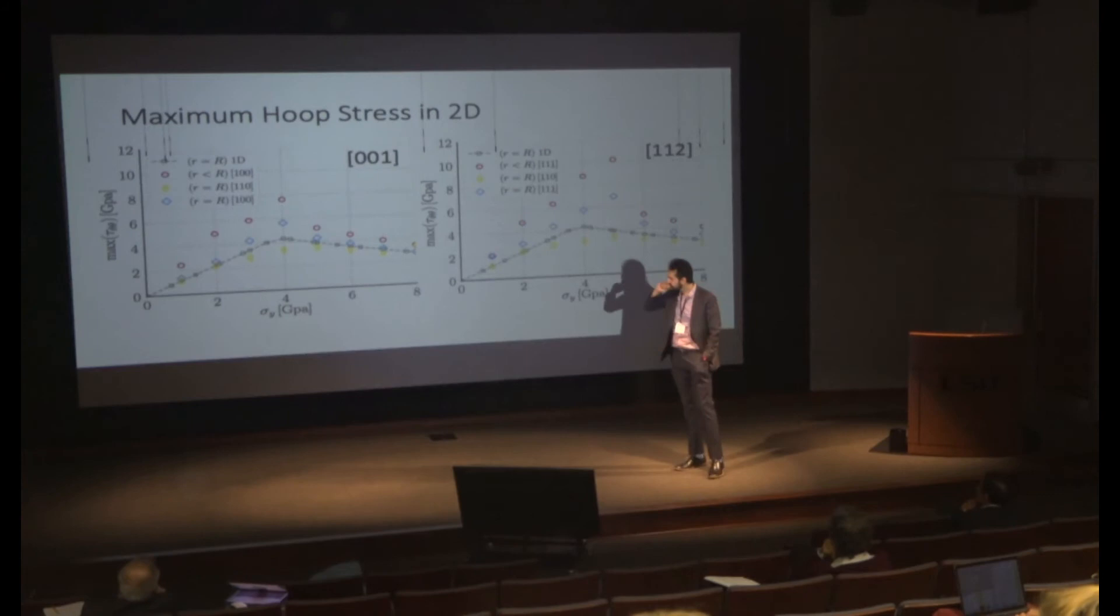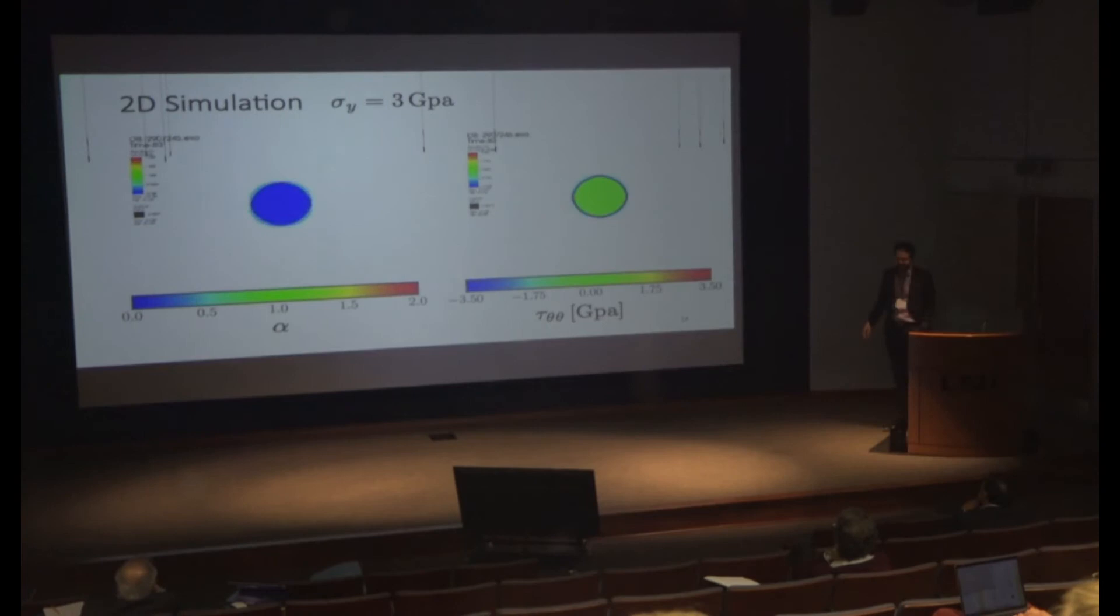Being a fracture person, what does that mean? That means if plasticity leaves enough room for you to get high enough stresses, you're going to crack. You're cracking, and you can also crack on the other side of my up-and-down curve, what we call the window.